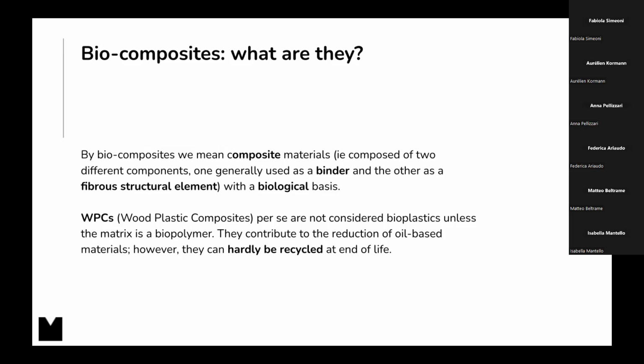Wood plastic composites are composite materials with, let's say, the matrix, which is a polymer, and the filler, which is wood flour. Usually per se they are not considered bioplastics unless the matrix is a biopolymer, but however they contribute to the reduction of the oil-based component in the material, and so they have a lower carbon footprint than similar material without the wood filling. On the other hand, there is a problem with recyclability, because of course, if you fill a plastic with some filler, then it would be much harder to recycle at the end of life. So that would make sense for very durable applications where the end of life would likely be incineration.